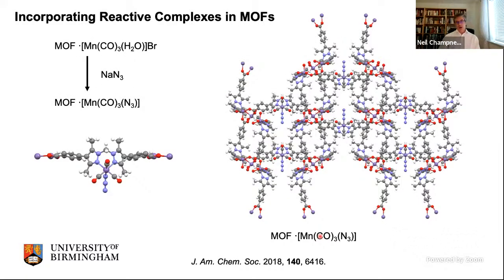So we have this manganese center bound within our MOF. So we started to wonder, can you actually do reactions at that manganese center? And the answer is quite clearly yes. So the first thing we do is we take our manganese tricarbonyl with a water and a bromide counterion, and we diffuse in sodium azide. Now the azide is a good ligand. The azide binds to the manganese center. Here you can see the azide bound to the manganese center, and you can see this on all of the azides in the single crystal structure of this compound. So every single one, essentially, has an azide bound to the manganese center.